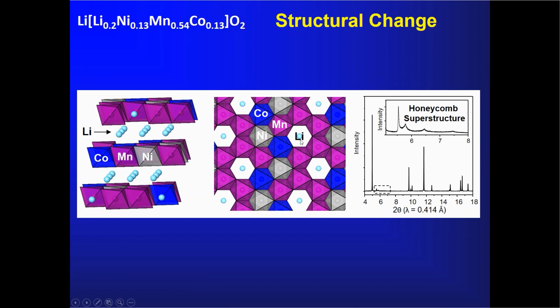But can we understand then how this is possible in this material? How is it possible, when you charge the material, when you extract lithium and oxidize oxide ions, to accommodate a molecular oxygen in the structure? So here's the crystal structure again. We're looking along the planes here. So here's the lithium layers and the transition metal layers, as I showed you before. And then if we have a sort of bird's eye view looking down this way, this is what we'll see.